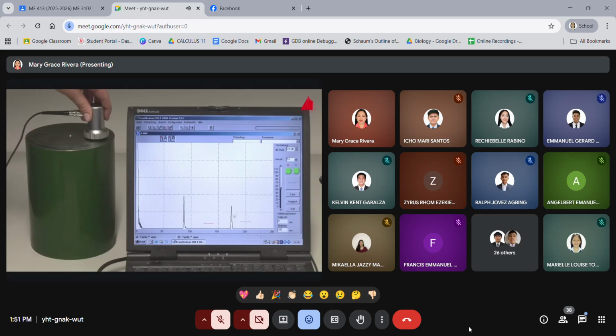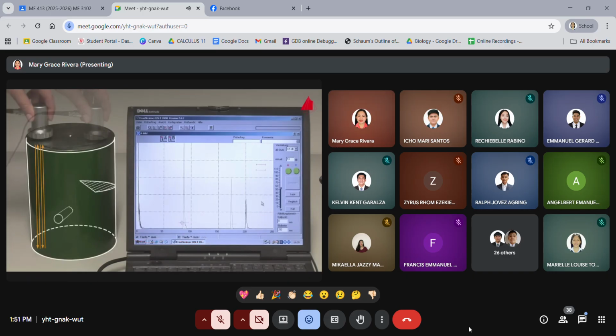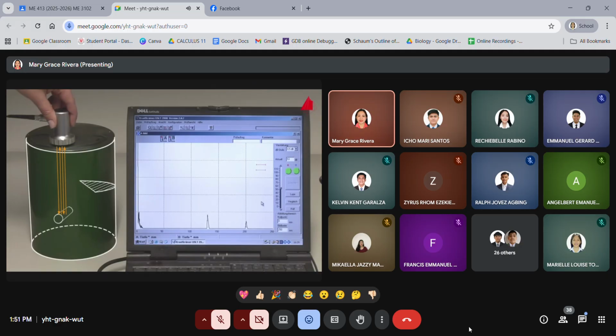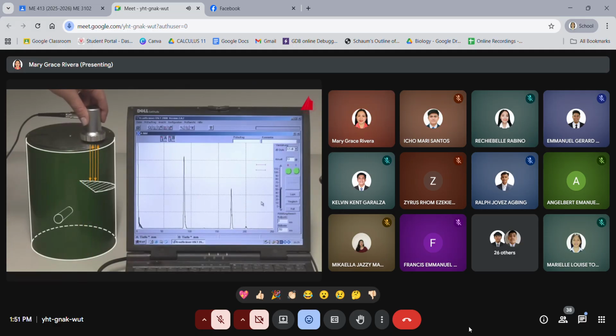Another echo indicates a defect in a depth of 87 millimeters. The second smaller echo at 174 millimeters is caused by double reflection on the same imperfection. And these are the defects. A drill hole and a saw cut. Filled up near the surface and painted, they are not visible from the outside. The drill hole in a depth of 130 millimeters. The saw cut 87 millimeters below the surface.